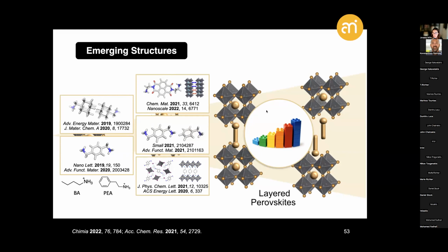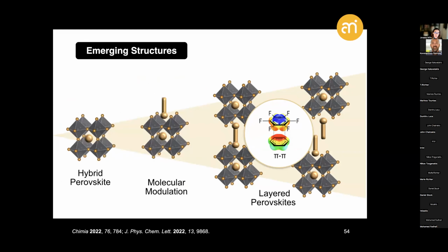Now, in this analysis of this variety of systems to control these organic assemblies, pi-based interactions were particularly relevant. And especially when attempting to control them by inverting the polarization of the benzene ring by perfluorinating it in order to access these more parallel rigidified organic assemblies controlling the properties of the resulting materials. To assess the possibility to achieve this, we have referred to two relatively simple model systems that involve this archetypical phenylethylammonium spacer or PEA, so a small aromatic ring with an ethylene linker and the A-cation mimicking ammonium termini that binds to the inorganic slabs, and its perfluorinated analog here labeled as FEA.